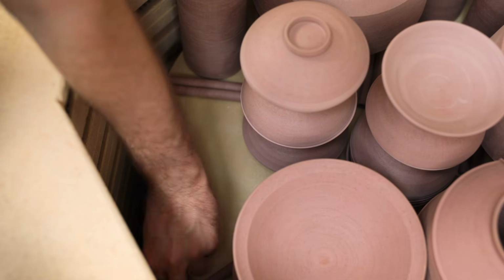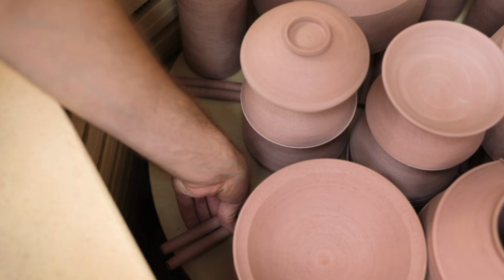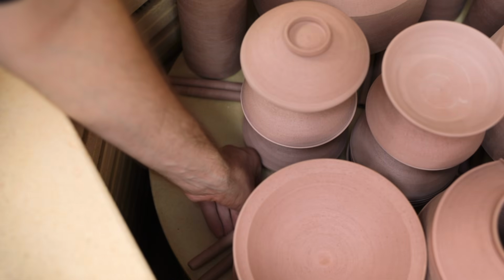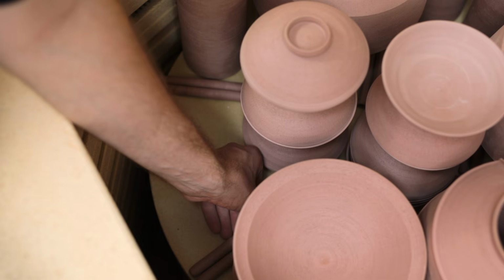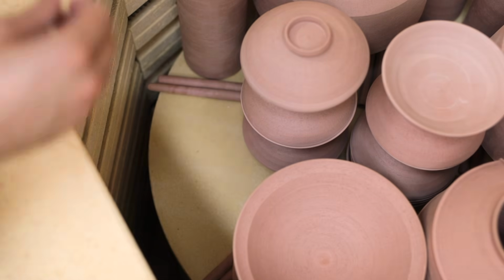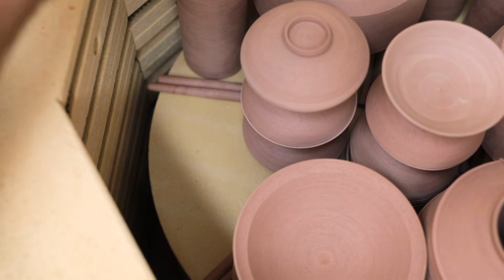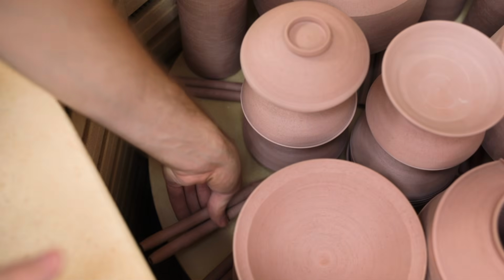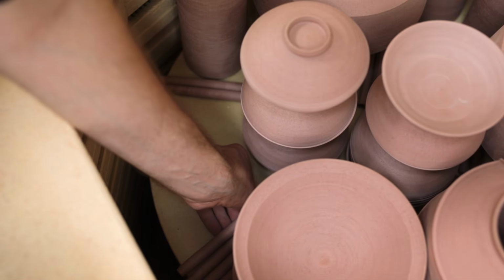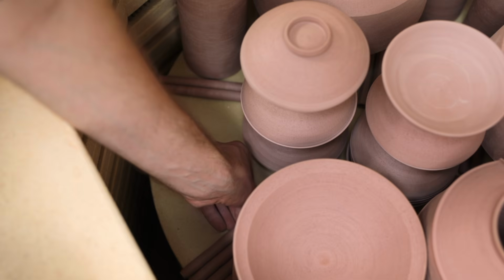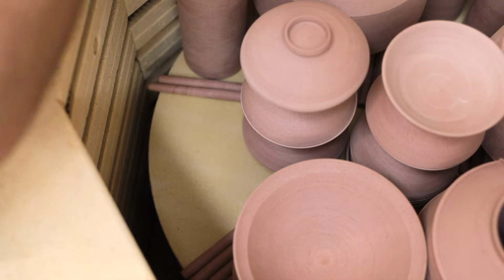Once fully packed, this kiln fires overnight, and usually by the time I'm in the following morning, it's already cooled down to about 450 degrees Celsius. But I don't usually open it until the day after that, when it's cooled down to about 40 degrees. Although if I am in a rush, this process can be expedited, but usually that's not the case.